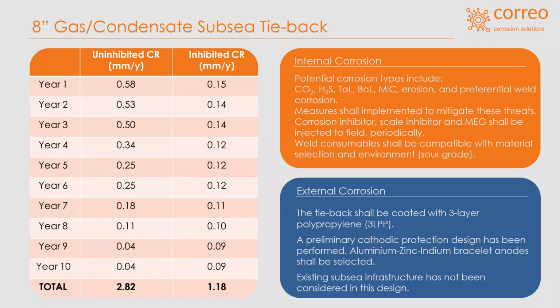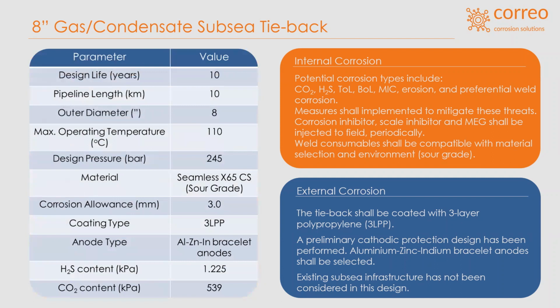We also then calculated an inhibited rate of using NORSOK M001 to give us a corrosion allowance of 1.18. So this meant, because we had a relatively low corrosion allowance, we could then select a seamless X65 carbon steel sour grade material for our line pipe. And we had to be wary of the potential corrosion and types that we would potentially face, such as CO2, H2S, top of line, bottom of line, microbial induced corrosion, erosion, and preferential weld corrosion.